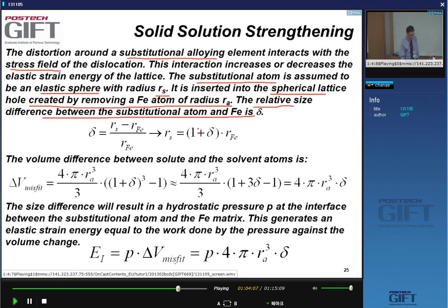So we use this parameter delta, and delta is nothing else than this ratio here: the difference between the radius of the solute and the iron atoms divided by R. So it's the radial strain, if you want. You can rewrite this: Rs is (1 plus delta) times R iron. And this is the important parameter. It basically gives us an idea of the amount of strain that you have, but it's a linear parameter. So you can calculate the volume difference